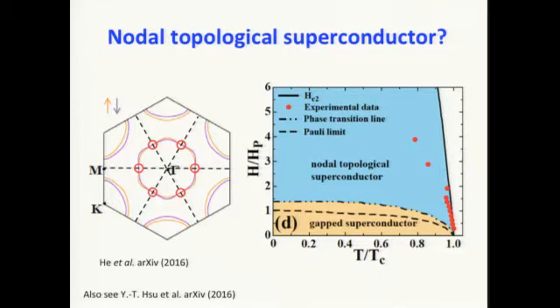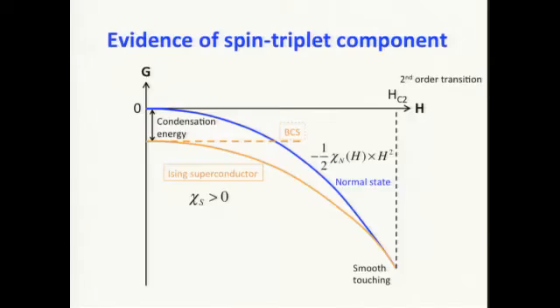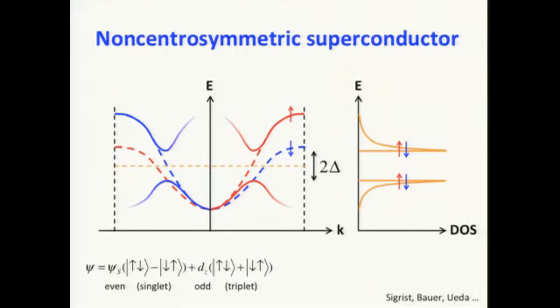The triplet component, the dz here, a rough estimate is basically the spin-orbit splitting at the Fermi surface divided by the bandwidth. So in this case, it's 0.1 eV divided by 1 eV. It's 1/10 of it. But do you always have singlet in the gamma pocket? In principle, not, because you also have spin-orbit interaction. So you still get this component. This component is gone only at the 6 points. Yeah, the 6 points.